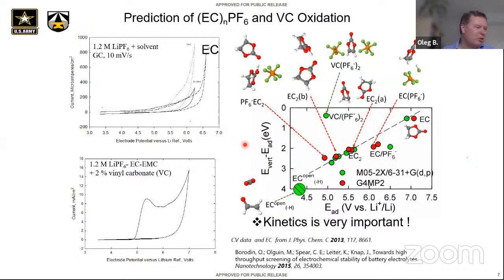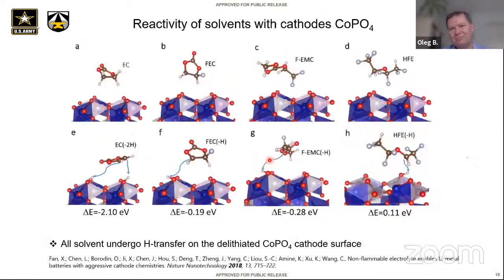A previous presentation had a graph that showed correlation between HOMO and oxidation stability, and in general there is a line, but there could be 2 volt deviations. So in my view, unless you don't care about 2 volt differences, you can use it reliably, but most often 2 volts is really what makes things work or not work. And the second corollary from here is that the majority of the solvents are not stable, right? So HOMO LUMO, what are you looking for? You're looking for stability. I haven't seen a solvent, except a heavily fluorinated one, which would be stable. Understood. Thank you so much.